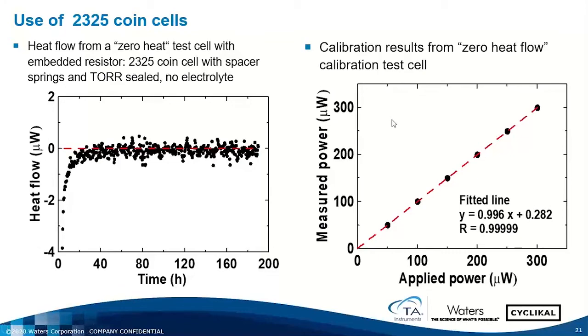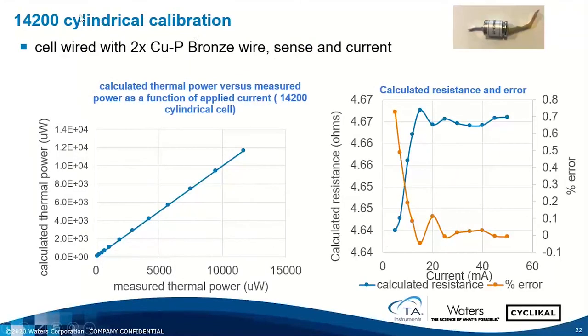For larger cells, this is for a 14200 cylindrical cell. It's approximately a 1/3 AA, wired with double-stranded copper phosphor bronze wire for both the sense and current. This is a cell that's approximately 100 times higher capacity than the coin cell. And on the left here, we see the calculated thermal power versus the measured thermal power after calibration. And we can arrive at some pretty high thermal powers. Typically, we're working more down in this range.